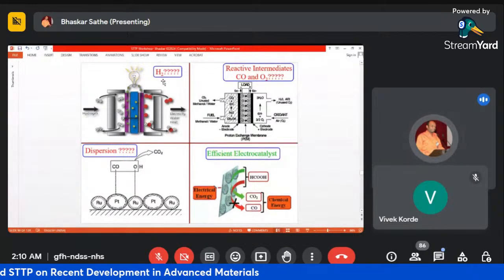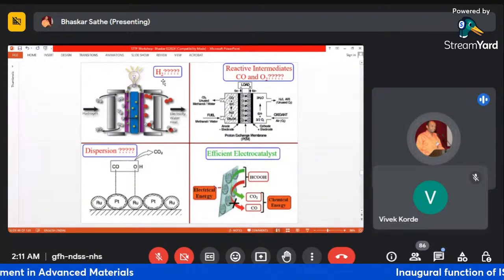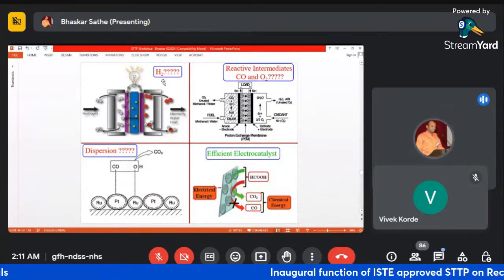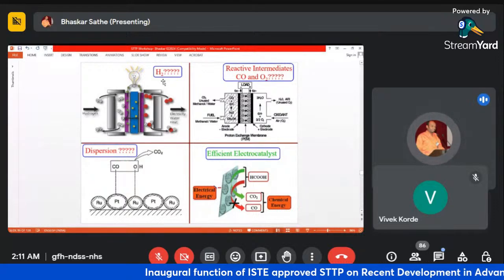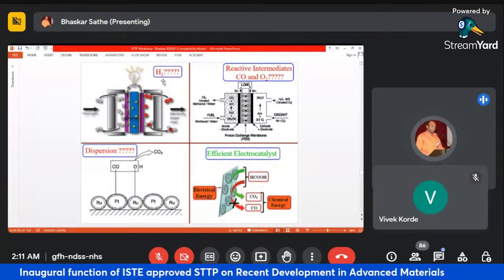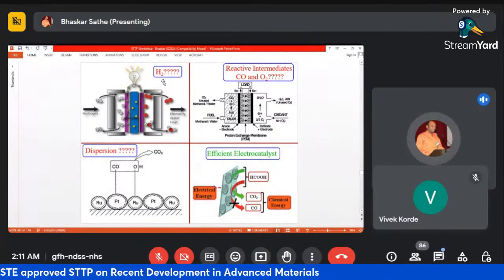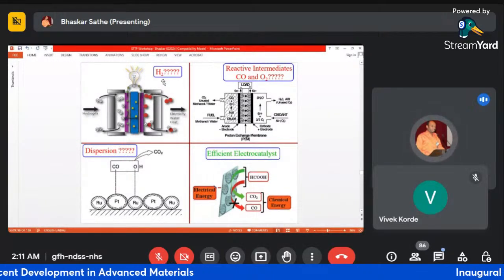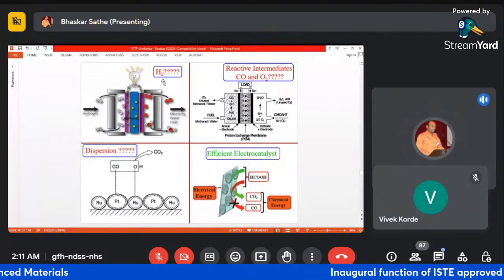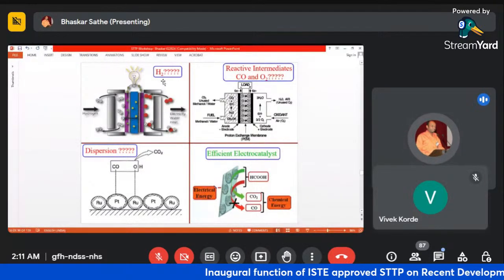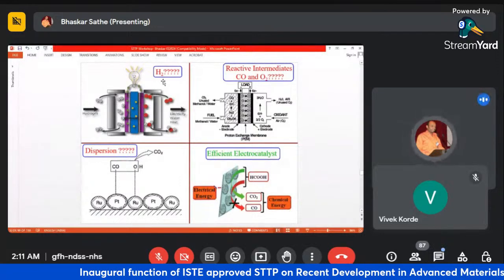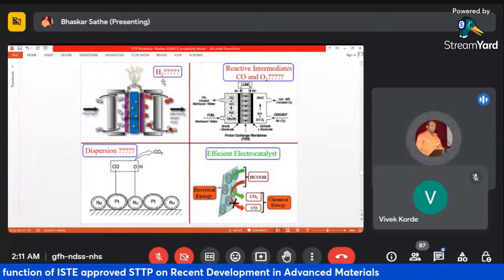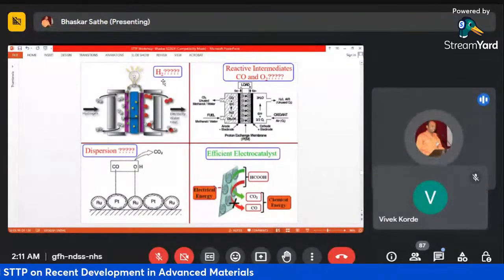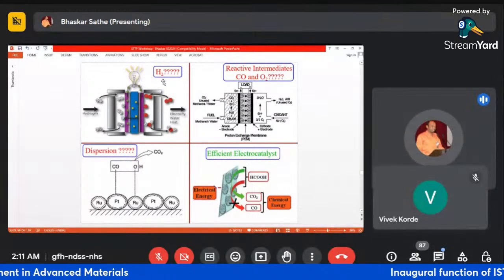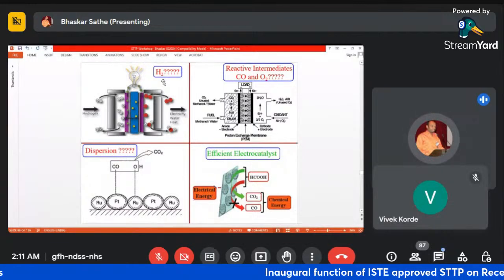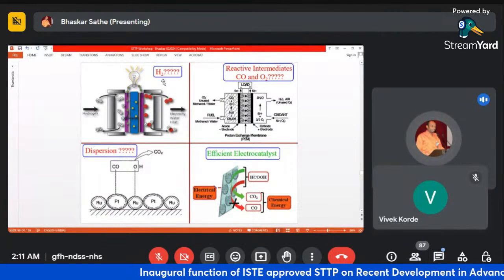As we know, self-cleaning is a good approach for electrodes to make them sustainable. So if platinum is the main catalytic system and it corrodes because of the irreversible binding of a strongly binding ligand like carbon monoxide, which is the intermediate species from the burning of the fuel, then to clean it, if you have ruthenium nearby, this will be sensitive to the OH. So the OH plus CO will give carbon dioxide, and the carbon dioxide will come out, and the platinum will be fresh, ready for the next reaction.